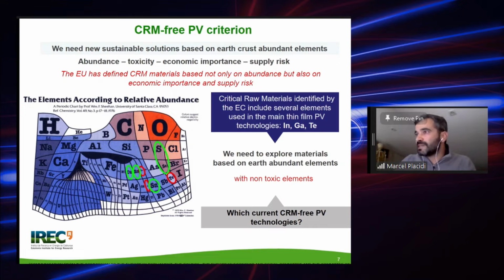So if we look at these materials, we can see that gallium, indium, and tellurium, which are forming the CIGS, the chalcopyrite, the copper indium gallium selenides, and the cadmium telluride, are critical raw materials. So this is not good in case of a massive deployment of this technology. So we need to explore materials based on earth abundant elements, and ideally also with non-toxic elements.